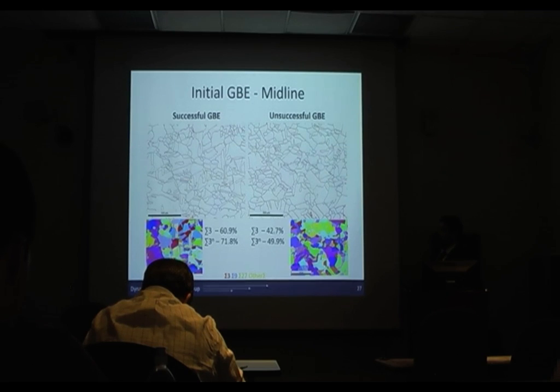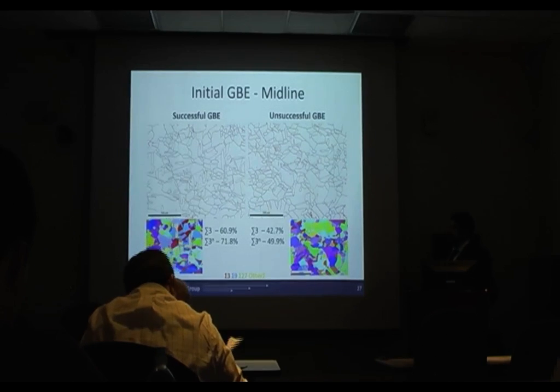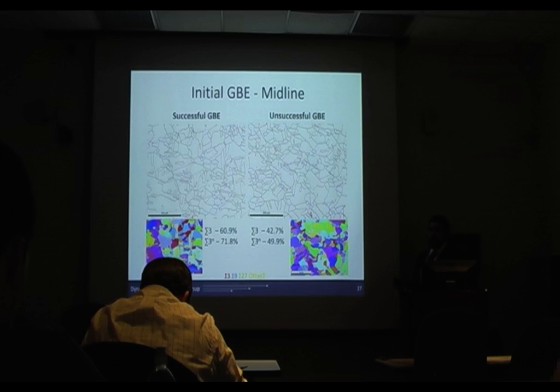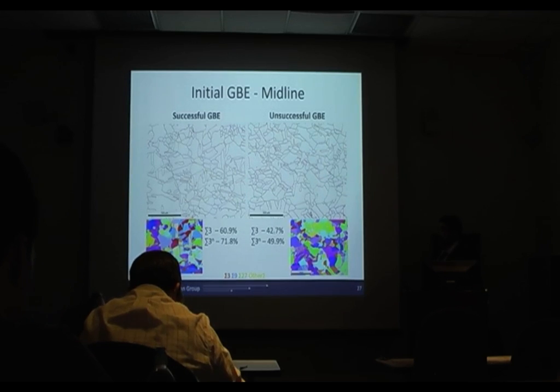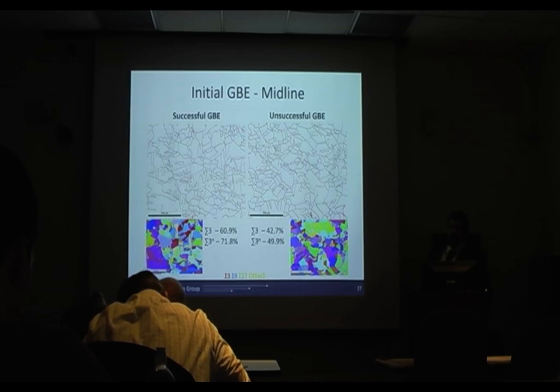The grain boundary maps are shown in the top, but the big thing is our sigma 3 to the n, which when I say that here, it's the sigma 3, sigma 9, and sigma 27s added together. The total fraction in the left map was 72%, which is pretty good, but it was only 50% in the right map, which is much more indicative of the length fraction expected for an annealed microstructure.